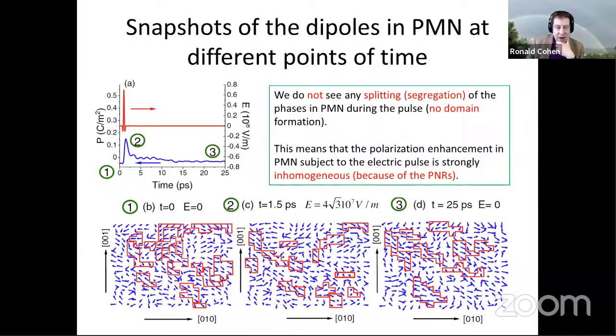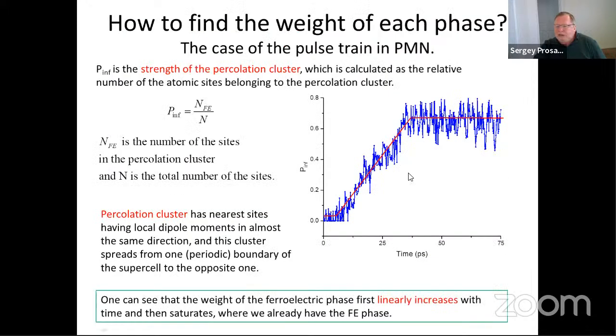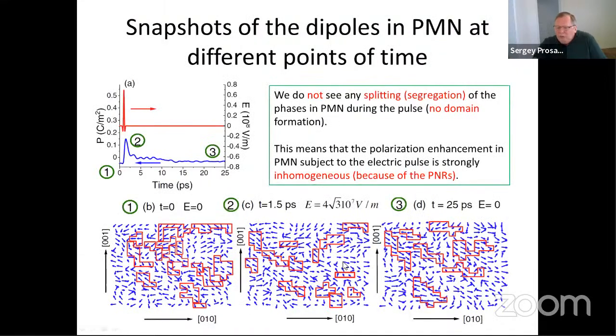I see. So you're saying you're not seeing a bulk ferroelectric state. You're seeing a reconfiguration of the polar regions. Absolutely, because for example, if we take this polar nanoregion, then we should look also in the upper and in the other planes. It can go through other planes to proceed. So from this picture, we definitely see that the connected cluster does exist, and it is increasing in size. But from looking at the one plane, we don't see this. Yeah, I see what you're saying.